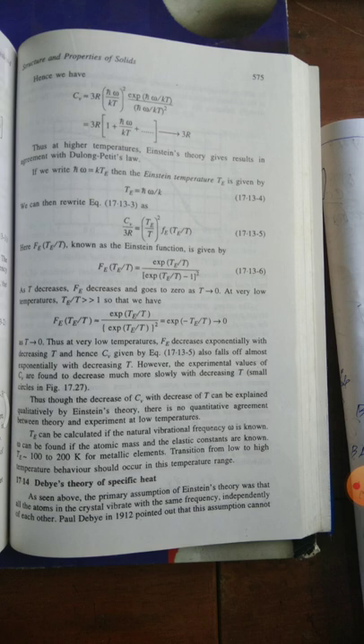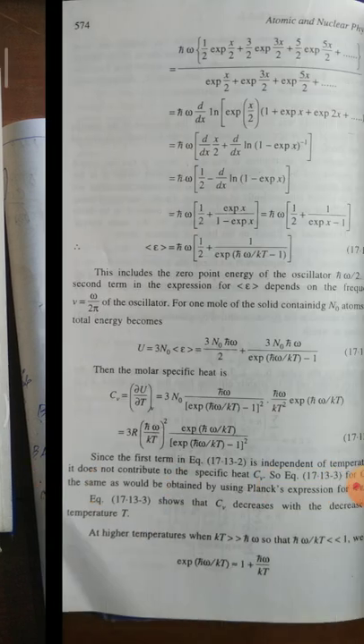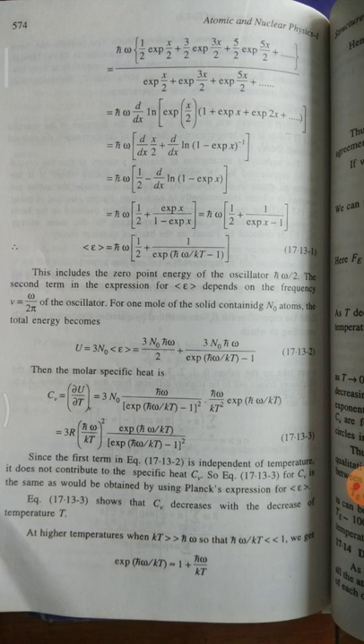Thus, at higher temperature Einstein's theory gives a result in agreement with the Dulong-Petit law. If we write ħω equal to kθE, then the Einstein temperature θE is given by θE equal to ħω by k. We can rewrite the equation as Cv equal to 3R (ħω/kT) squared into exp(ħω/kT) by exp(ħω/kT) minus 1 whole squared.